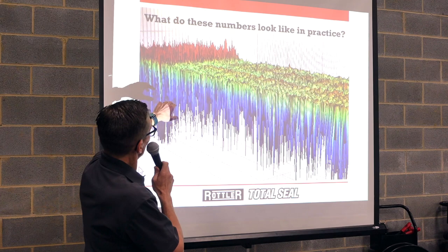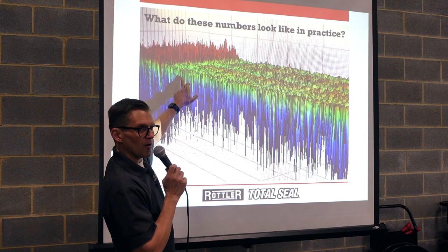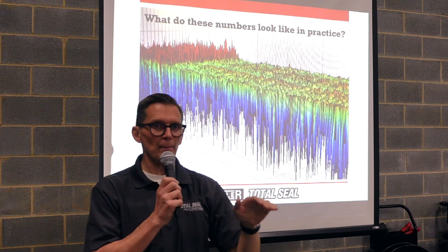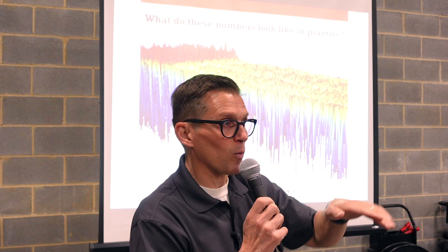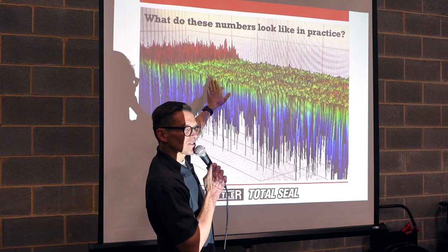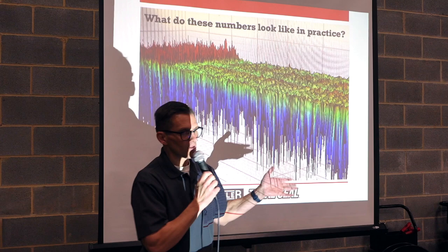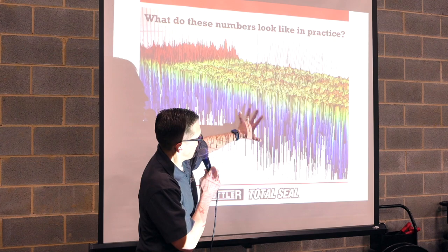You can see that little bit of shade of green here is just slightly less than all the others. That's exactly where the ring stopped. And if you zoom in on it, top rings are barrel faced. You can actually see the barrel on that spot because that's right where it stopped. But then as the ring moves away, like that water skier, what's it doing? It's getting thicker and thicker and thicker. And you can see there at the very end, the red's coming back up. So all these areas down here in blue, those are the valleys.